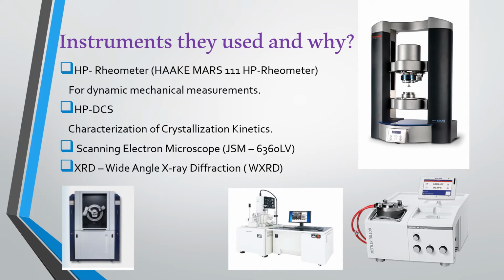Like I said, they used the HP rheometer for dynamic measurements to follow crystallization behavior by monitoring the storage modulus and viscosity, at various rates and temperatures, in certain atmospheric conditions. In this case, they used a modified high pressure rheometer. We will be discussing it when we discuss the experiment later, under compressed carbon dioxide in a pressure range of 0.1 to 28 megapascals. So it's a little bit high pressure.